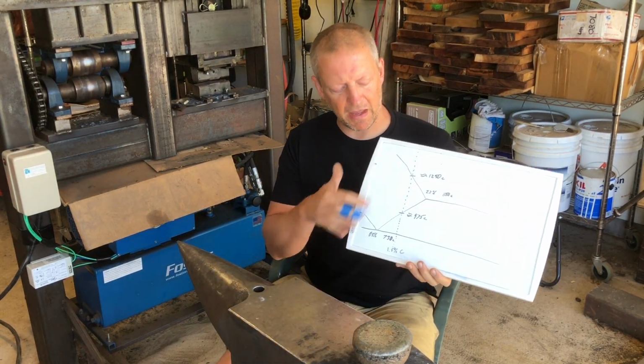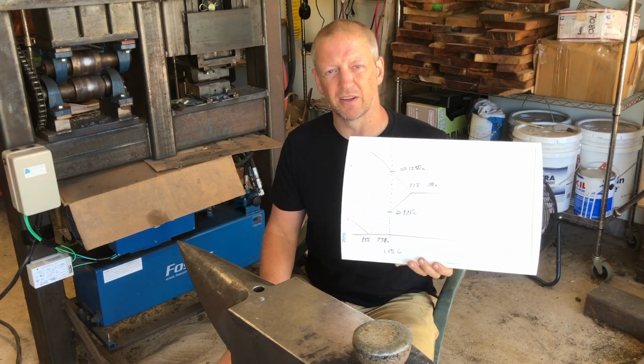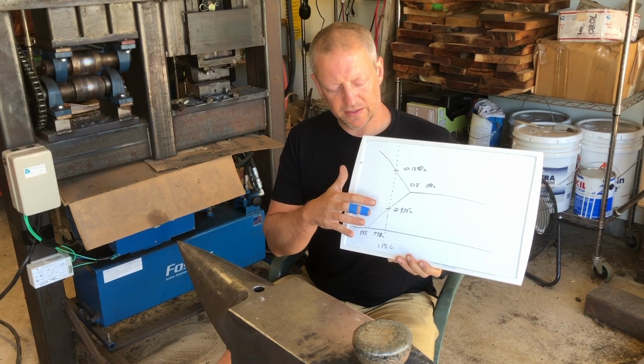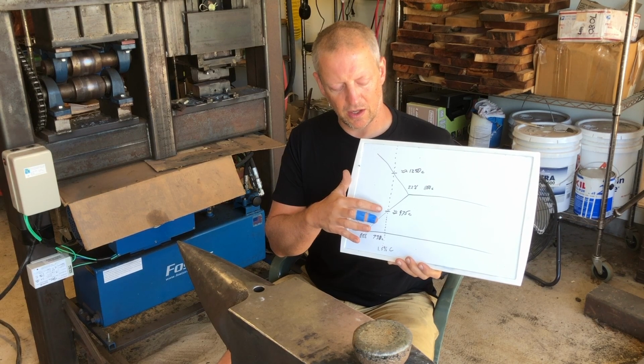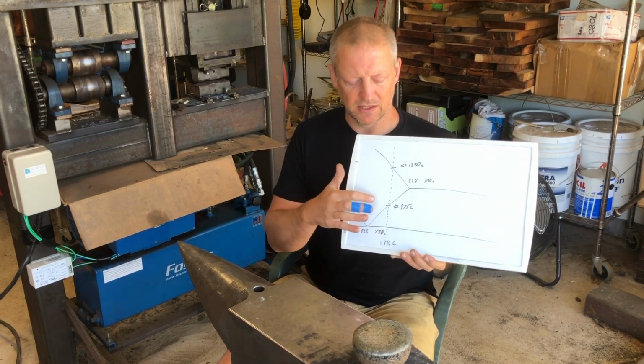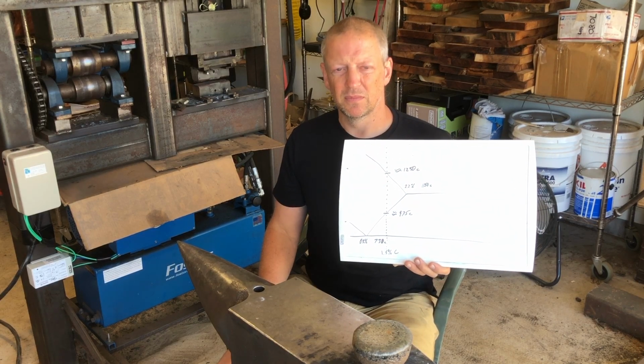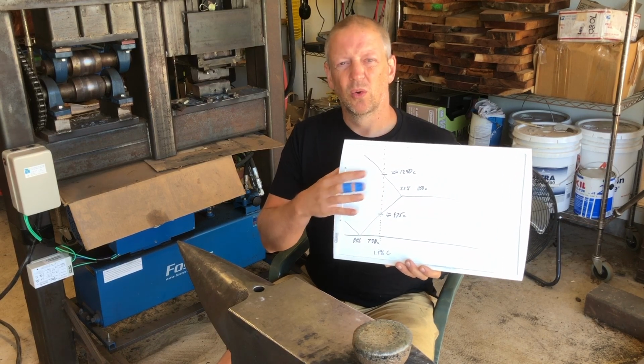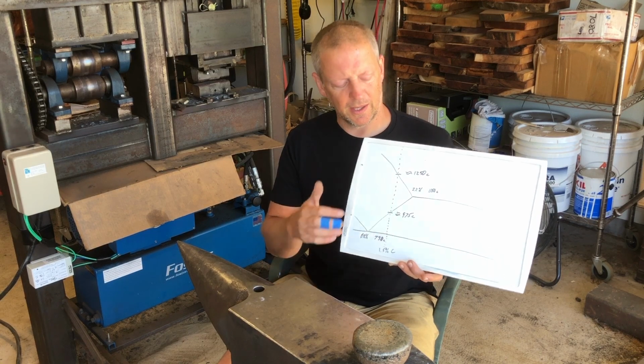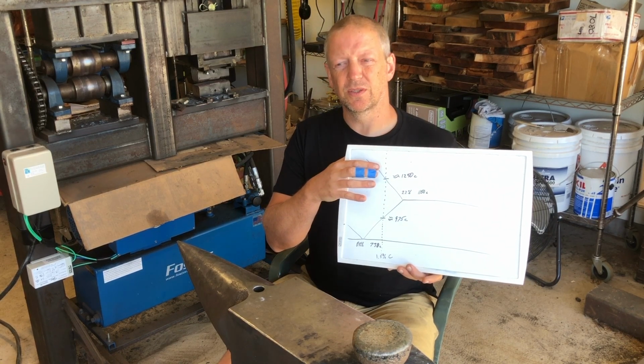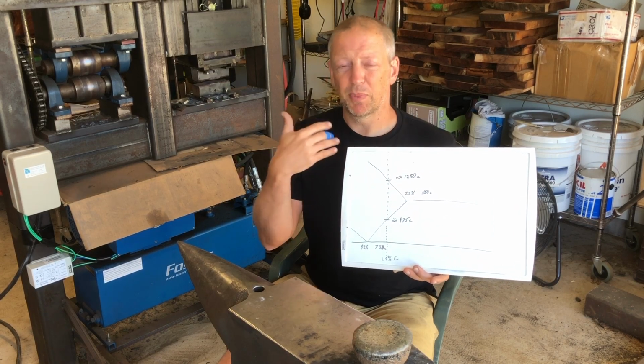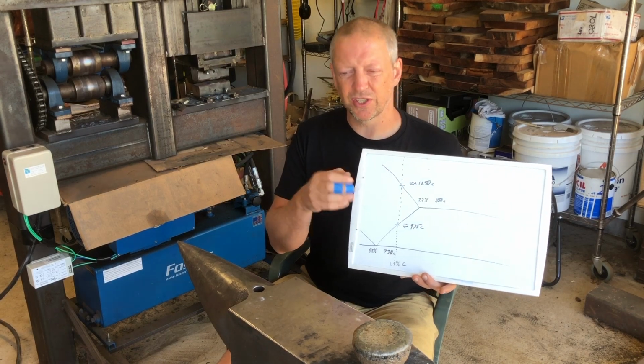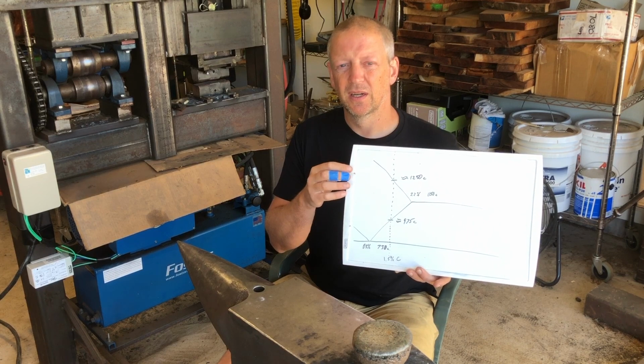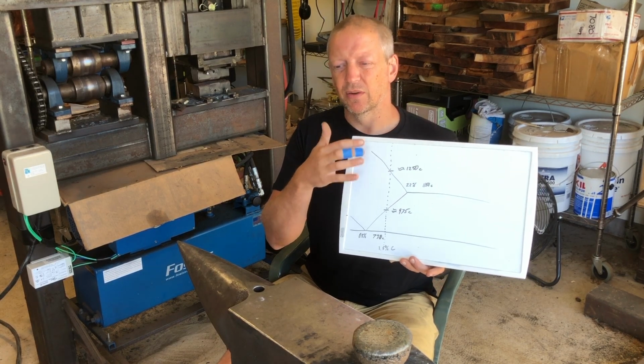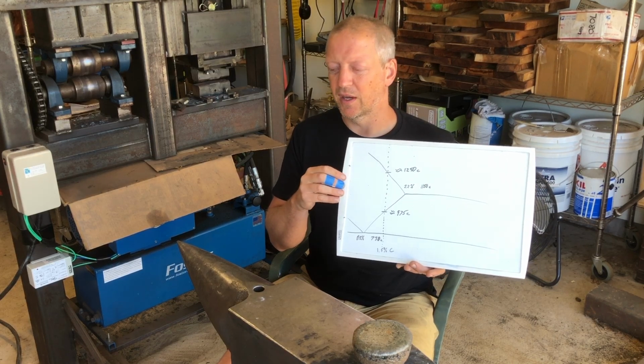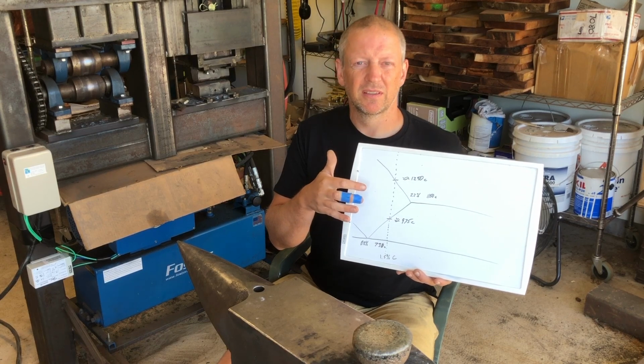And again, referring back to the chart, or to our phase diagram, the key things to keep in mind here are going to be what your assumed carbon content is, and therefore where your ACM line is, and similarly, where does your slushy zone start? Because if you roast up into the slushy zone, my opinion is that's not going to do you any good. Once you get up into the slushy zone where you're getting partial liquid in there, basically what you're going to be doing is just replaying the initial solidification process. So not going to necessarily be super helpful.